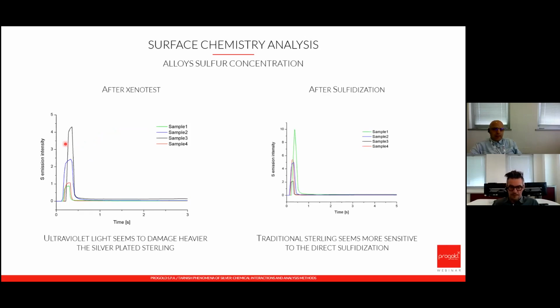Now, summarizing some general results of this research, we could say that sulfur damage is more severe for the silver-plated sterling under the ultraviolet test, maybe due to damage or photodegradation of the anti-tarnish additive on the galvanic coating. Whereas the direct sulfidization in the humid box seems to be more aggressive on simple traditional sterling, probably for the sole presence of copper having an amazing affinity for sulfur.